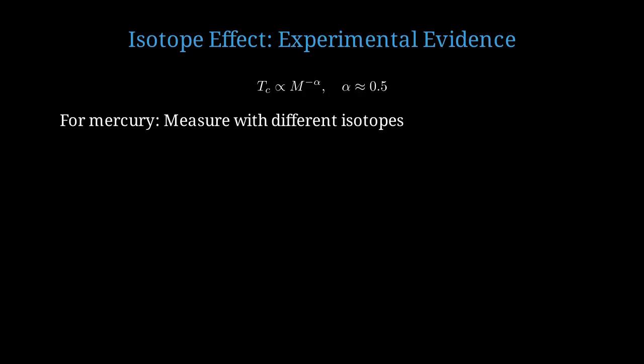One beautiful piece of evidence for phonon involvement is the isotope effect. If we replace mercury atoms with heavier isotopes, the critical temperature changes. The critical temperature scales as T sub c proportional to m to the minus alpha, where m is the isotopic mass, and alpha is approximately 0.5 for most superconductors. This proves that lattice vibrations, whose frequency scales as 1 over square root of m, are essential. For mercury, if we use mercury 198 versus mercury 204, which differ in mass by about 3%, we observe a T sub c difference of about 0.06 Kelvin. This is exactly what the BCS theory predicts.